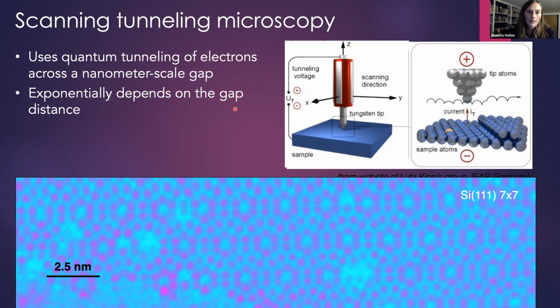This is an example of an image we took in our lab at UNH. The purple circles are silicon atoms, and the blue lines and traces are the spaces between the silicon atoms. And this is a really beautiful surface. This is the silicon 111 plane. And this is called the 7x7 reconstruction. It means that at the surface of the material, the atoms rearrange themselves into this really cool pattern. So that in itself is really cool.